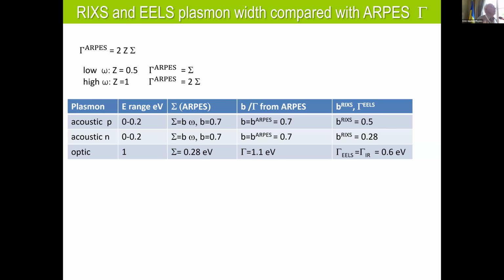So the scattering rate is equal to the self-energy, but for higher energy, Z is equal to 1, which means it should be twice sigma. And it all roughly agrees, basically, yeah? Yeah, not exactly, but at least qualitatively. And so this is qualitatively for all the cuprates of interest for you.